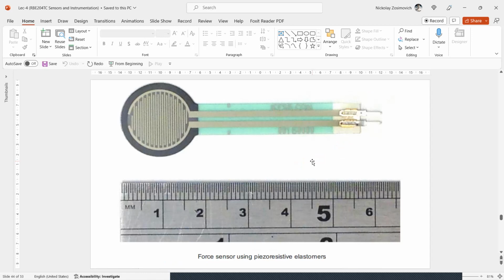Besides the nonlinear behavior, unfortunately, most piezoresistive materials also show hysteresis, poor reproducibility, and creep, mainly because of permanent position changes of the conductive particles within the elastomer after being compressed, or lack of elasticity. The typical behavior of conductive elastomers is still not fully understood, although many attempts have been made to model the piezoresistive properties in relation to composition and manufacturing methods. Despite the poor performance of the sensing properties, some useful designs have been constructed and applied for a variety of applications where accuracy is not an important issue.